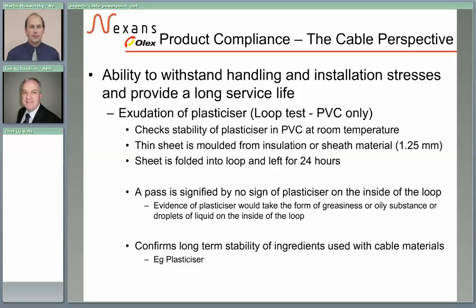It's performed by moulding a sheet of material to a specified length and width, and then folding into a loop and left for 24 hours. And stability of the plasticizer will be observed if there are no signs of greasiness or droplets of liquid on the inside of the loop. Fairly simple test, but it's just a mechanical test that has to confirm that the plasticizer is stable within the PVC material. So again, it's another way in which the long-term stability of the cable materials are achieved.